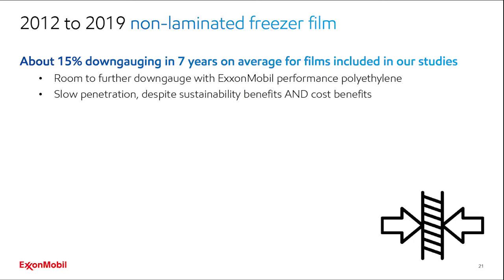Typically in 2012, the average thickness for non-laminated freezer film was 65 microns. And in 2019, as mentioned before, we are at 55. But still, there is room to further reduce that thickness with ExxonMobil performance polyethylene products, and Marcus will further explain that later on. So it means that for now, the penetration of the thinnest solutions is not yet there. All those solutions are not yet on the market, despite sustainability benefits and also cost benefits, as mentioned by Richard in his introduction.